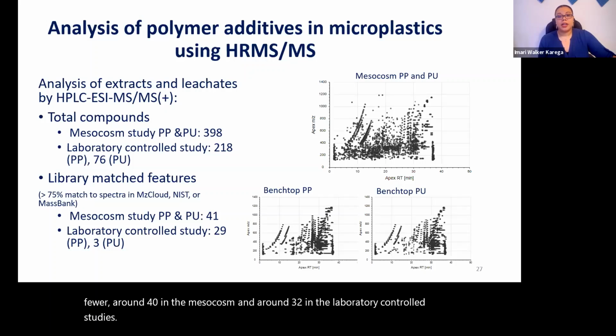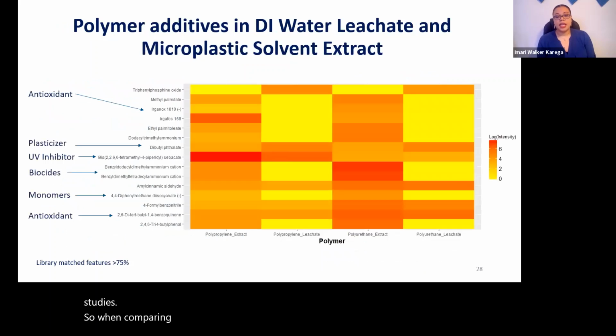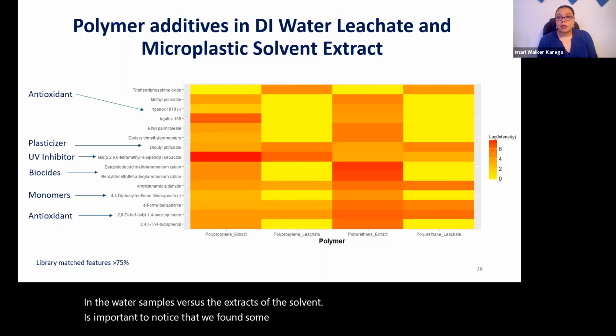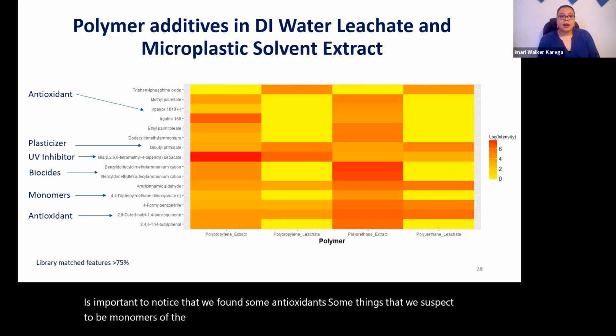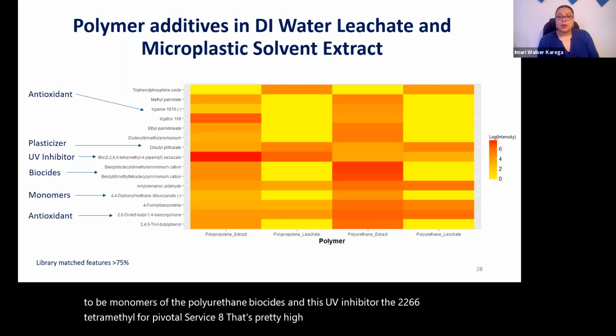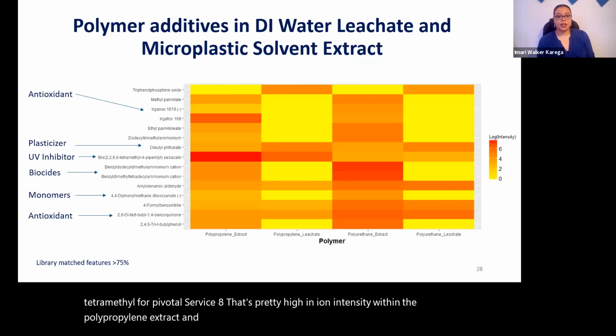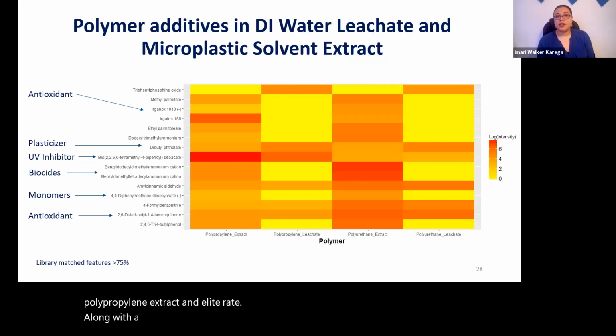So when comparing compounds in the water samples versus the extracts of the solvent, it was important to notice that we found some antioxidants, some things that we suspect to be monomers of the polyurethane, biocides, and this UV inhibitor, the 2,2,6,6-tetramethyl-4-piperidinyl sebacate, that's pretty high in ion intensity within the polypropylene extract and the leachate, along with a few plasticizers and fatty acids.